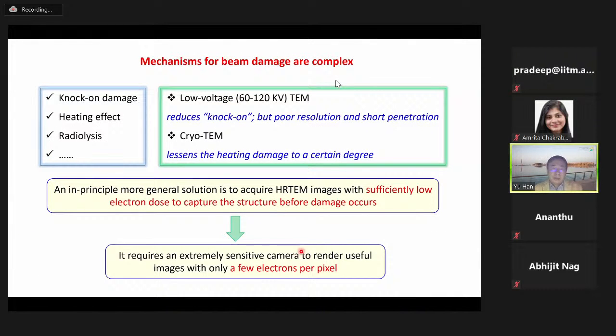So how to reduce the beam damage effect? In fact, the mechanisms for beam damage are quite complex, including knock-on damage, heating effect, radiolysis effect, and so on. Okay? One can use the so-called low voltage TEM technique to reduce the knock-on damage. This technique is particularly useful for imaging two-dimensional materials. However, low voltage leads to poor resolution and also short penetration depth. And more importantly, low voltage may sometimes even give negative effects if the damage is governed by mechanisms other than knock-on. So low voltage TEM cannot be generally applied to all applications.